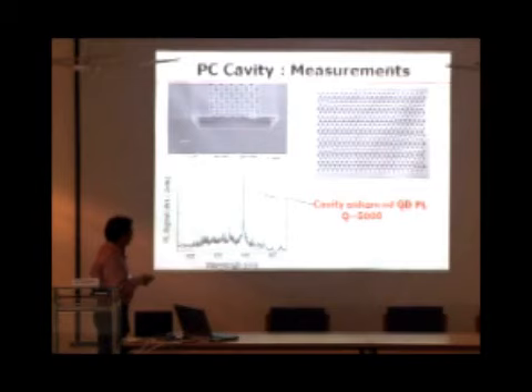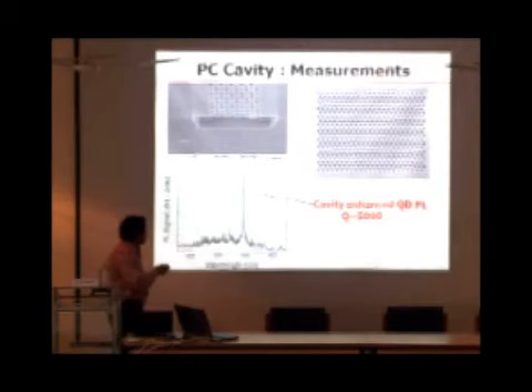Yesterday Professor Hill talked about Purcell enhancement. So this is how it looks like - these small spikes are because there are lots of quantum dots, but when the quantum dot resonance matches with your cavity, you have enhancement in your luminescence. From the line width, we estimate the Q to be about 2000.